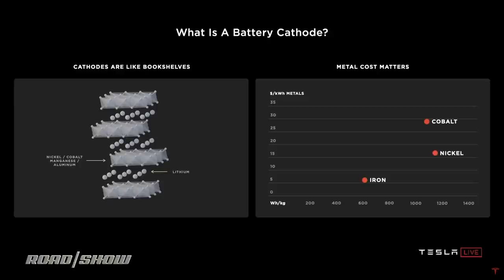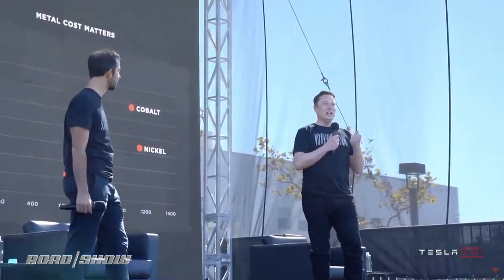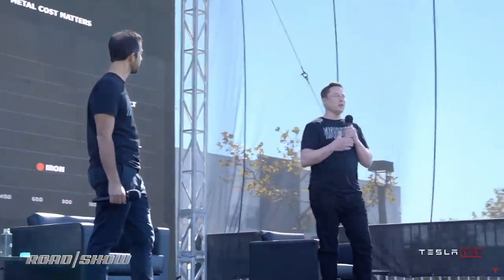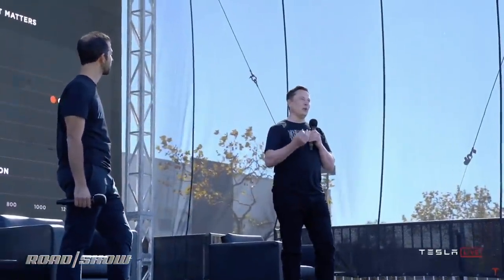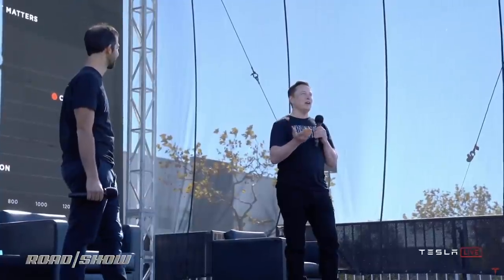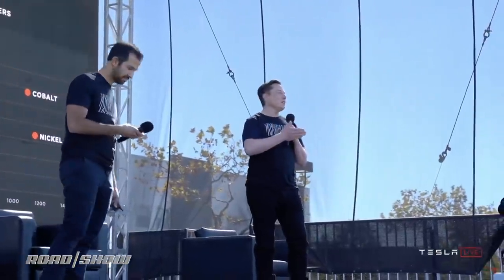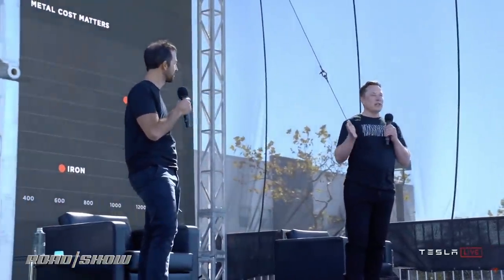It's tough to exactly figure out what the right analogy is to explain cathode and anode, but a bookshelf is probably a pretty good one in the sense that you need a stable structure to contain the ions. So you want a structure that does not crumble or get gooey, or basically that holds its shape in both the cathode and the anode. As you're moving these ions back and forth, it needs to retain its structure. If it doesn't retain its structure, then you lose cycle life and your battery capacity drops very quickly.